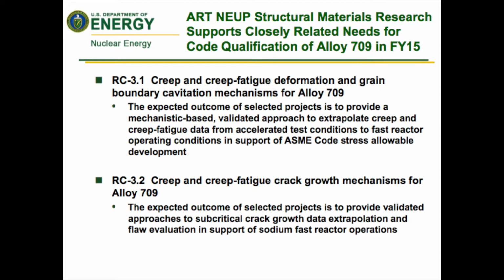Creep and creep-fatigue deformation and grain boundary cavitation mechanisms for alloy 709. And the outcome we are hoping to get from this is to provide a mechanistic-based, validated approach to extrapolate the creep and creep fatigue data from the accelerated test conditions that you can get in the laboratory to the long-term fast reactor operating conditions that are needed to support the extrapolation of the ASME code stress allowables out to 500,000 hours. So that's topic number one.